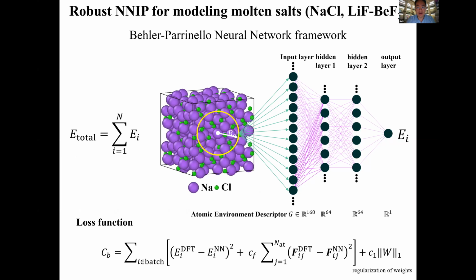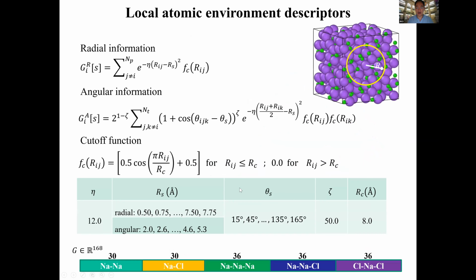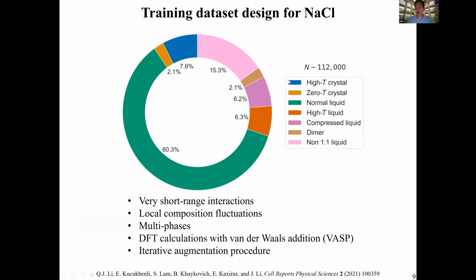So in the early days, we collaborated with Professor Kaxiras's group in developing Behler-type potentials for specific systems, such as sodium chloride, lithium fluoride, beryllium fluoride, molten salt systems. Here we have 2 hidden layers, and we're using the Behler approach, with radius-dependent and angle-dependent symmetry functions. Generally we fit the forces and the total energy, and we also do some regularization to prune out some of the weights. Here you see the radial symmetry functions, the angle-dependent symmetry functions, and these are our training data sets.